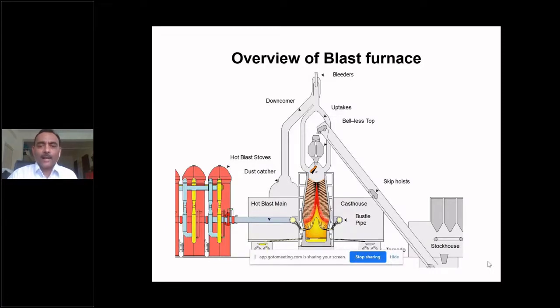They are silica, alumina, some magnesium oxide, manganese oxide, etc. All these raw materials are not needed in the furnace, but in the process they will go inside. So we have to remove them. For that, we have to add limestone, because limestone contains lime. So lime will make slag by fluxing all these undesirable oxides. And for sending hot air, we have stoves.